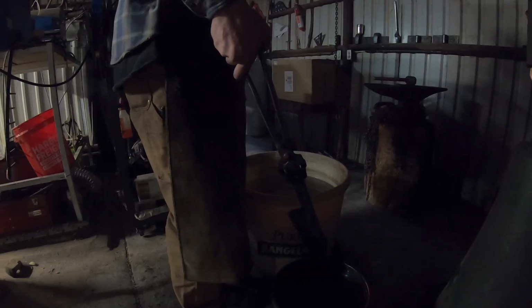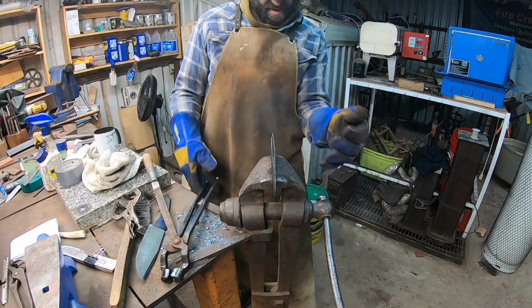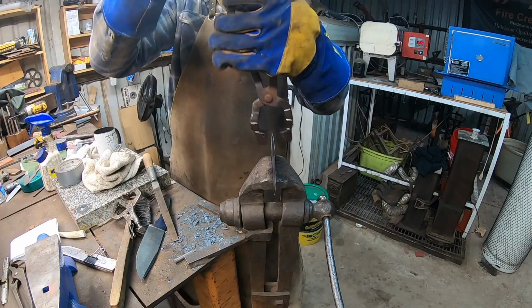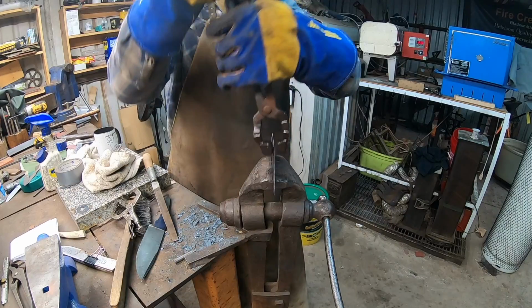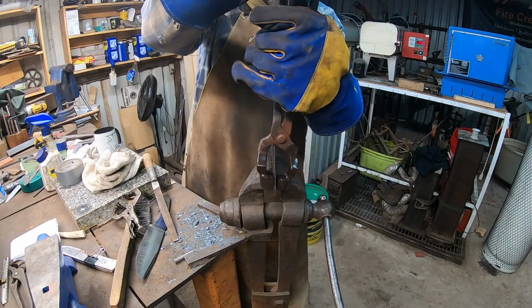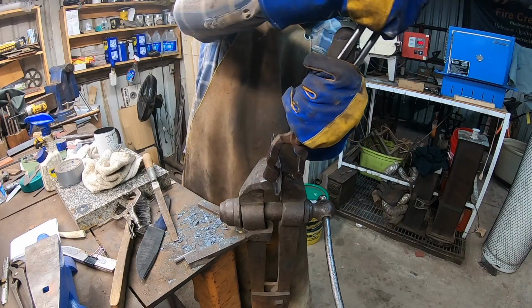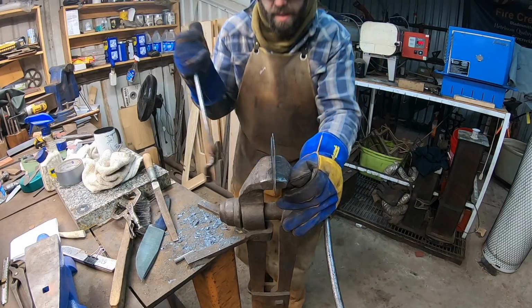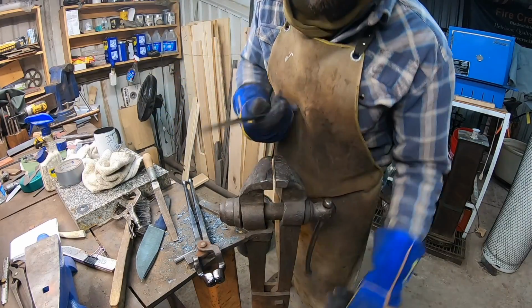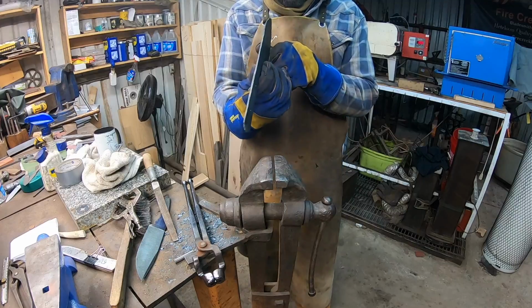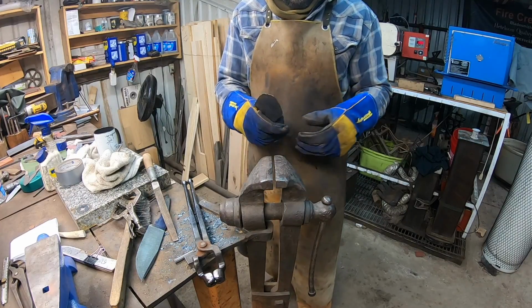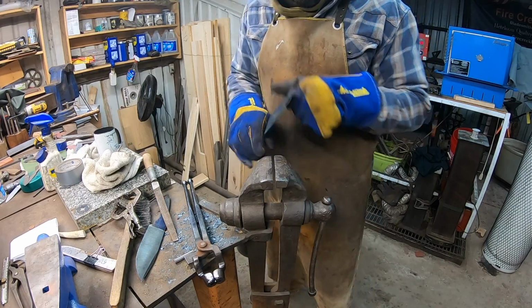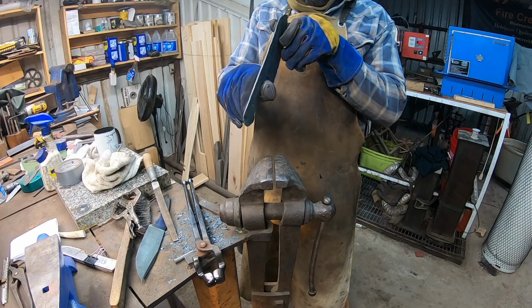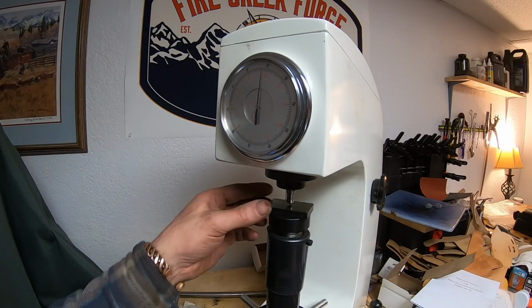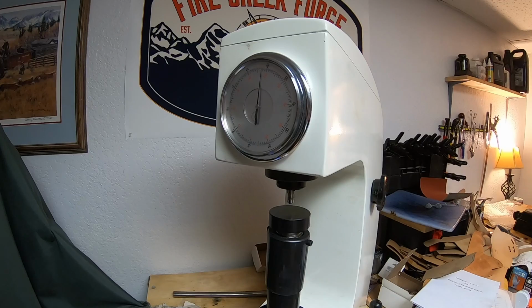The reason I'm using a water quench is because this steel, as with traditional Japanese bladesmithing steels, requires an extremely fast quench in order to harden to its full ability. Even a fast oil like Parks 50 would not be adequate to harden this steel. Some straightening, and this is another benefit of the mild steel cladding, is that you can work with the blade a lot more than you could otherwise.